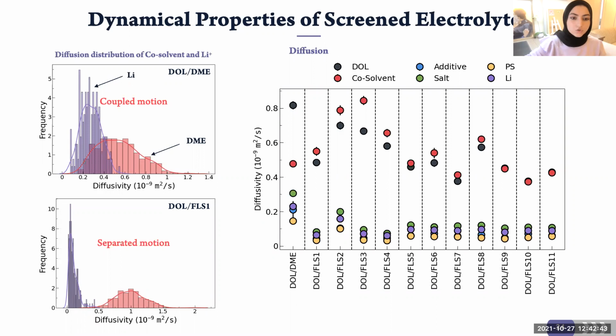Overall, if we look at the diffusion coefficient for the different systems, we see that the diffusivity of the ionic species in these electrolytes is impacted negatively compared to that of DOL/DME, but that is expected because we have more degree of clustering and lower polysulfide solubility in these electrolytes. But if we take a closer look, we can see that the electrolytes that were screened in this study have better dynamical properties than the one that has been extensively used and proposed in the literature, which is FLS4, especially FLS2 that has better ionic diffusivities than that in FLS4.